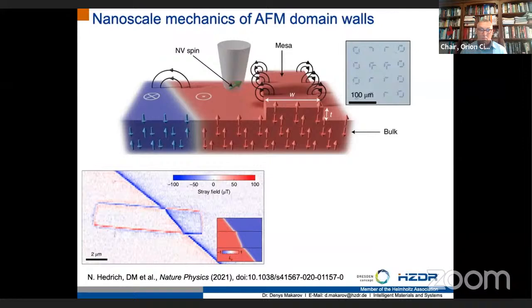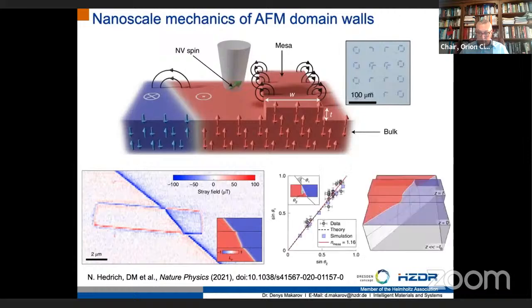As you can see, the domain wall in the interior of the sample is actually a straight line, and only at the location of the mesa it acquires a very interesting modification of the profile. You can obviously see and recognize such kind of an S-shaped profile at the location of mesa. We performed theoretical analysis of this S-shaped curve and came to the conclusion that this is a pure geometrical effect, and the tilt of the domain wall at the edge of the mesa is determined by the thickness to width ratio of the mesostructure. In this case, the tilt of the domain wall at the mesa can be controlled by the geometrical parameters of the material.